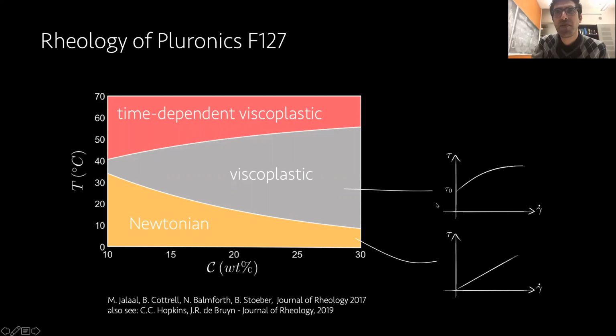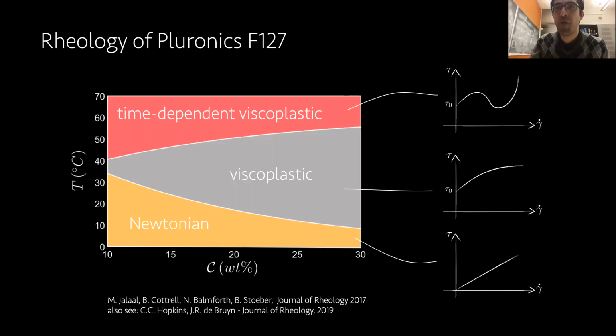And what we also found out, if you go to very high temperature, something weird happens. You get negative viscosities in your flow curve. We couldn't repeat those experiments. More recently, the group of John De Bruyn, Hopkins and De Bruyn, in this very nice Journal of Rheology paper, looked at the rheology of the same fluid and found that this behavior is most likely associated with the long relaxation time of the polymer. Have a look at these two papers if you're interested in the rheology of this.